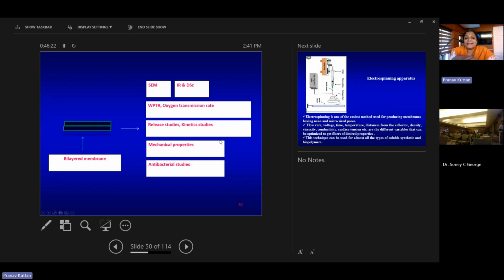Then, as I said, the antibiotic was added to this membrane. So the release of that antibiotic was evaluated, and the kinetics of the release. Then the mechanical properties, it should have enough strength, so that was evaluated. Then, since it is an antibacterial agent, the antibacterial activity of this ciprofloxacin also was evaluated. So this is how it is going to be.